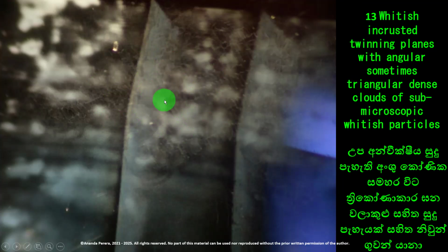Whitish encrusted twinning planes with angular, sometimes triangular, dense clouds. It is like clouds. A little bit of spiral look also there. Submicroscopic whitish particles are here. These whitish particles are giving the evidence regarding the beryllium treatment.